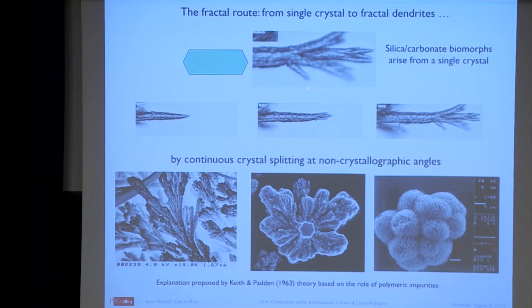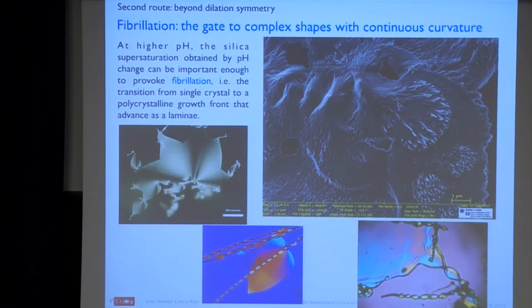It's a non-crystallographic branching, and when you have iteration of the splitting process, you obtain a fractal structure, a cauliflower-like fractal structure that looks externally like globular shapes. Okay, and now what happens if you increase the pH? You increase the pH by a mechanism that we don't really know yet how it occurs.